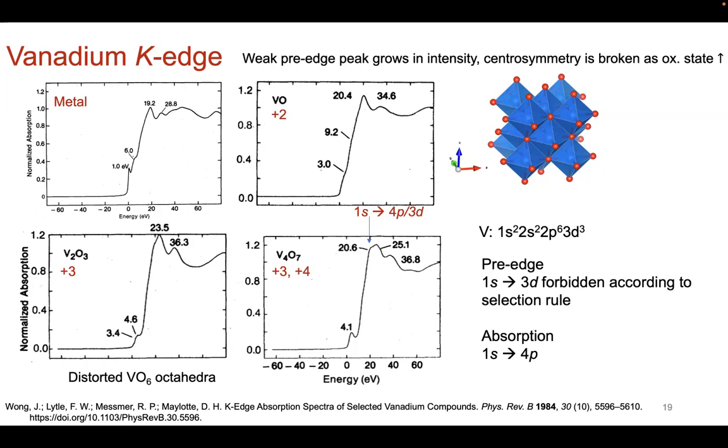The xy will actually split off from that degeneracy, and so you now have two in the t2g that show up. And that's what also hybridizes with the 4p. So you have this split off because of the 3dxy orbital breaking degeneracy in the t2g.